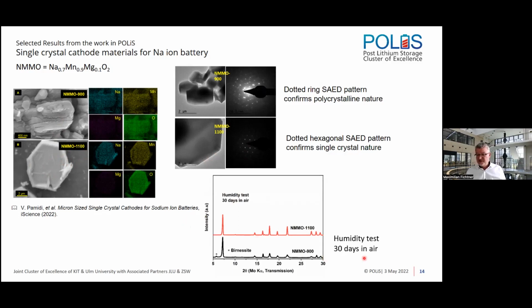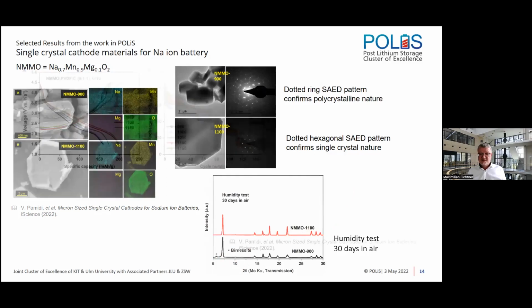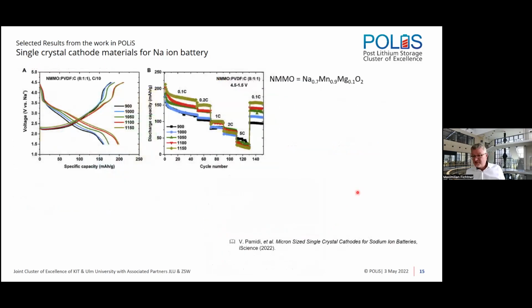You can leave them in air, in humid air here. After 30 days, you find that the polycrystalline material reacts with the humidity in air. Even in the XRD, you see additional phases like the Birnessite here. And this is not visible with the single crystal material. So this is more chemically stable, but it's also performing better.